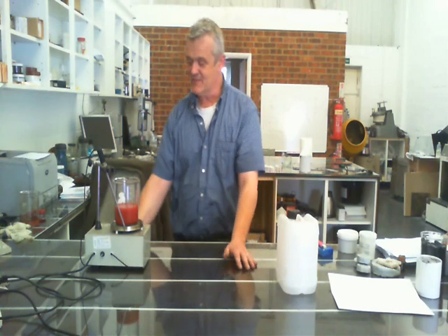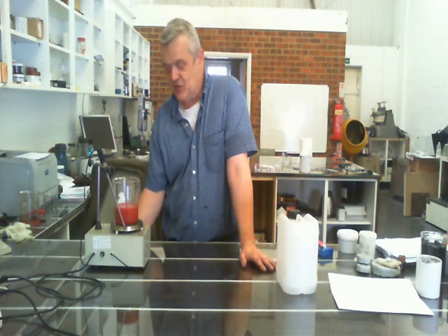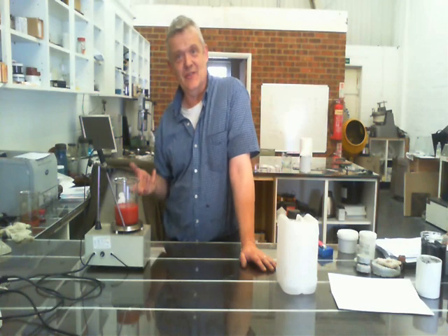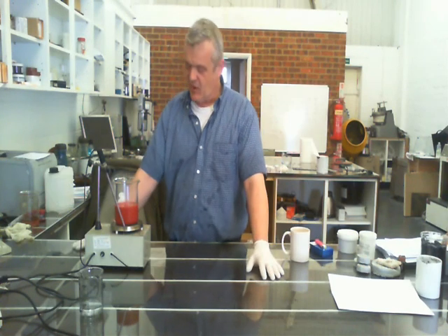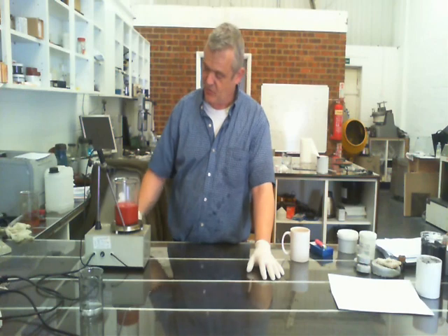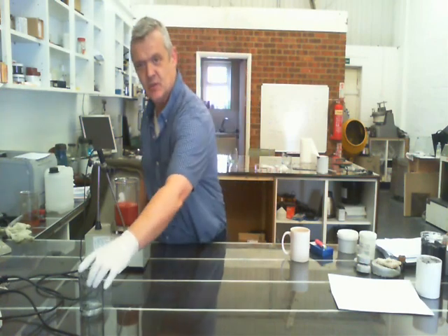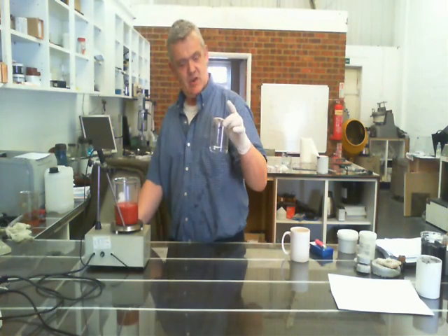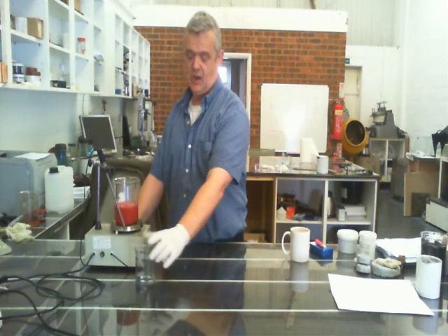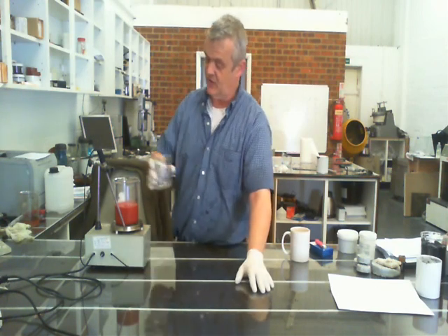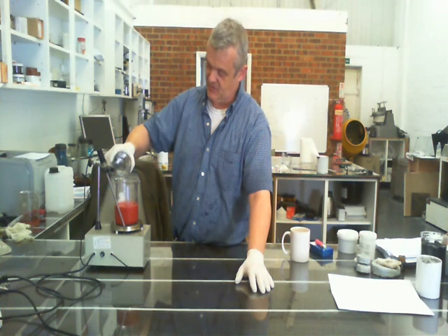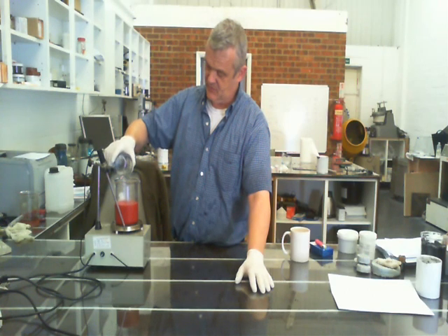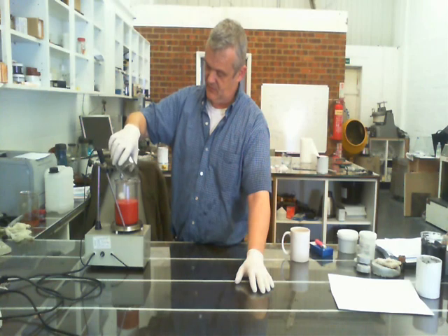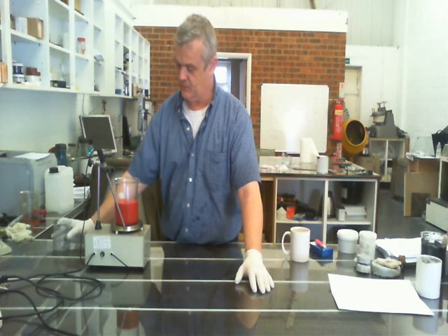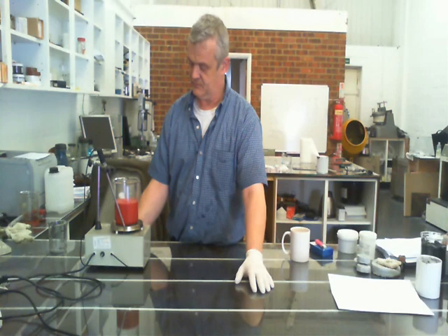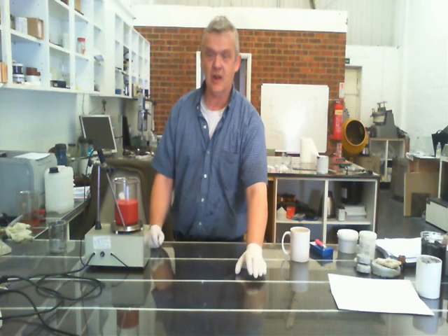All you do is give that a stir for half an hour until it has thoroughly mixed through in the gelatin solution. So here we are 20 minutes later, and as you can see, that's mixed up rather nicely and the whole thing is distributing that throughout the gelatin. Now what I've got here is 40 millilitres of 85% formic acid, and all I actually do is add the formic acid to that. And then just leave it alone.